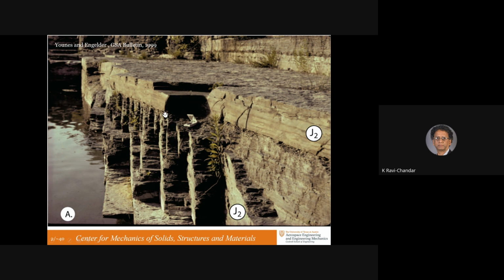The ground motion is such that this crack is under compression and shear. Shearing parallel to the walls of these cracks, parallel meaning movement in this direction, and movement into each other giving compression. As a result of this, from the original crack front, cracks start to grow into the uncracked portion, but they form a pattern as they go in there of steps or ridges or echelons. And this is the problem of interest. When and how do these cracks form? Can the traditional techniques of fracture mechanics allow us to calculate or predict that this is what should happen?